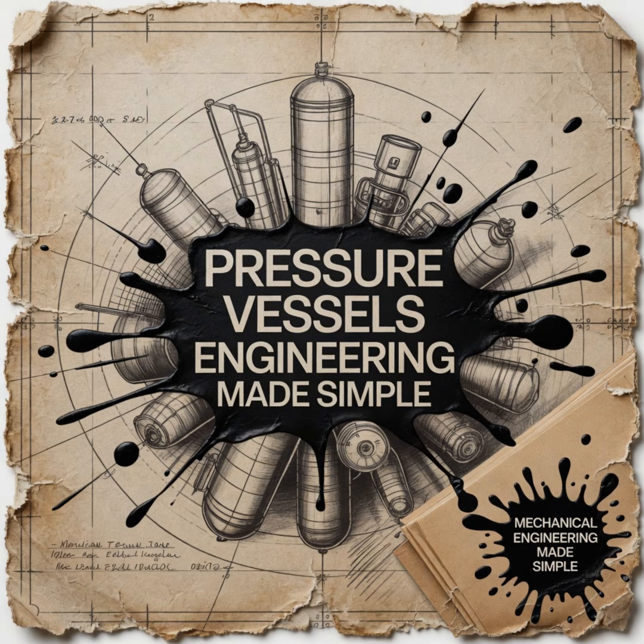So a void in the metal lets more radiation through. Right. RT is absolutely phenomenal at finding volumetric defects, things that take up physical space. A trapped bubble of gas like porosity or a chunk of glassy slag has much less density than the surrounding steel. The radiation passes easily through that void, hits the film, and creates a dark, easily visible spot on the negative. For volumetric flaws, RT is the gold standard. But I hear a but coming.